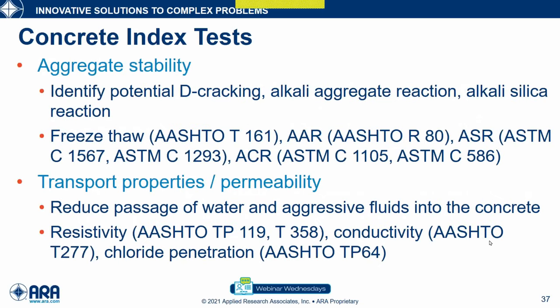You want stable aggregates, so you want to identify aggregates that have potential for cracking or expansion. There are many different reasons they expand, whether it's water or alkali reaction, ASR, and that causes the concrete matrix to crack. So there are different tests for your aggregate in terms of its potential to crack the concrete paste. And then the concrete paste itself, how permeable it is, to reduce passage of water and aggressive fluids into the concrete. And so there are tests for resistivity, conductivity, chloride penetration.